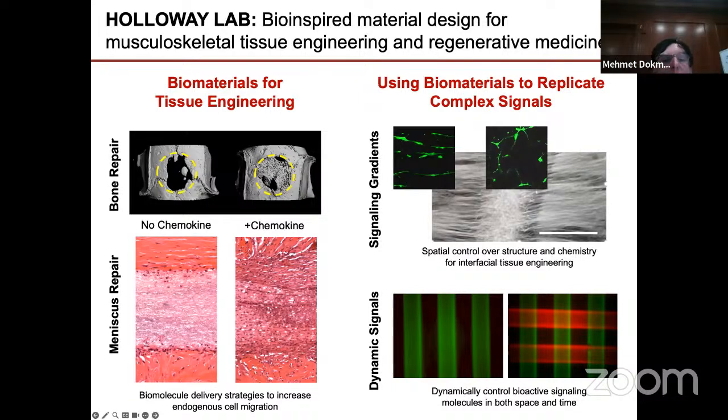Thank you. Another question is, did you try photoreactive collagen materials? In general terms, for natural biomaterials, what happens to these gradient structures after hydration? Is the structure retained? This is a good question. We've done a lot of work electrospinning hyaluronic acid, and you can get aligned hyaluronic acid, and even with the cellulose when it's magnetically aligned, but you can get aligned hyaluronic acid just by rotating the mandrel. And we've swollen these scaffolds in PBS and they maintain their alignment.